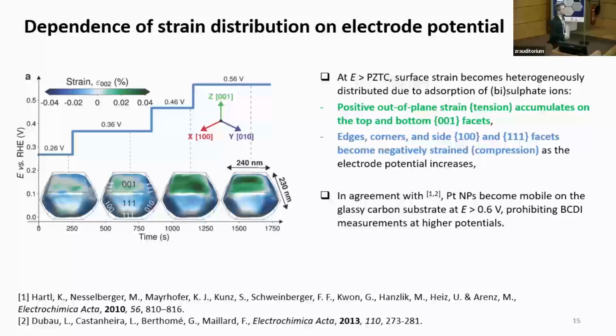Now, these are the results as a function of the electrode potential. So we increase from the potential of zero total charge, we go more positive. And what you may see on this particle is that the heterogeneity in strain distribution becomes more and more pronounced. So we got positive out-of-plane strain developing on this top and bottom facet, and the edges and corners are becoming more and more compressed as the electrode potential is increasing.